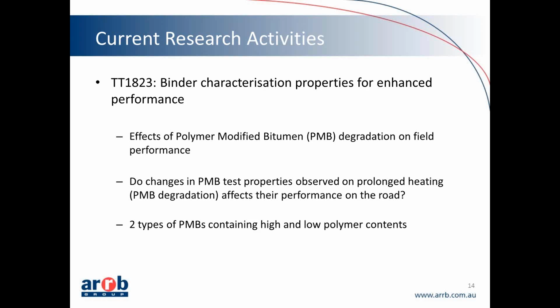Do changes in the polymer-modified bitumen test properties observed over prolonged heating, or PMB degradation, affect the performance on roads? Everybody that we've spoken to about this project had some sort of opinion on what they thought would actually happen. So this was really just an assessment of whether or not people's assumptions were correct, and it was quite a useful piece of research. And for that, we did two types of polymer modified bitumens containing high and low polymer contents.